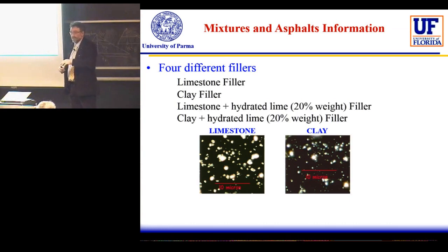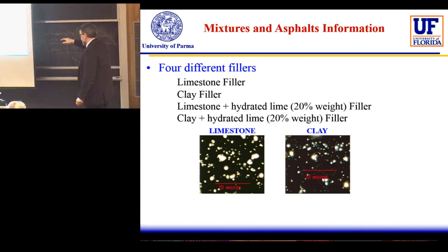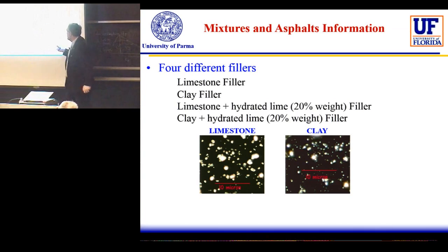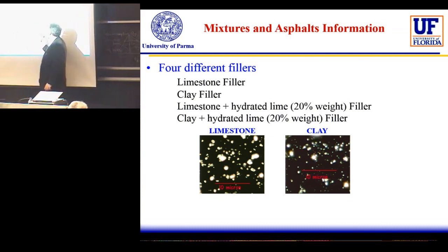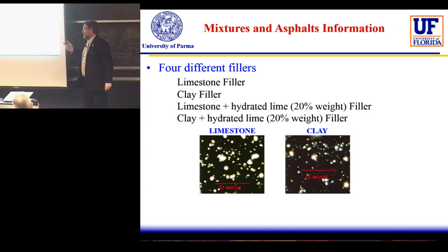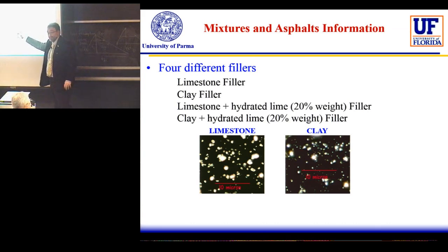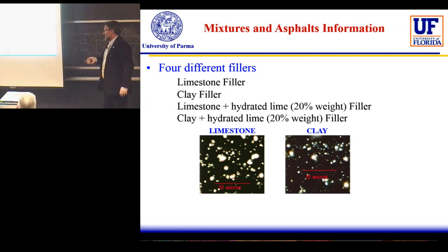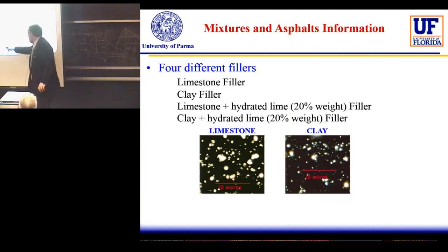Clay, I repeat, is something that you never find in the technology, but it is an artificial way to do that. And at the electron microscope, we were able to see that already in the dispersion of the filler, something changed if we use filler based on limestone and filler based on clay. I am honest, we are still not able to understand why this change happened, but something different appeared. So at the end we had 16 different mastics and 16 different mixtures. The same mastic was applied in the mixture.